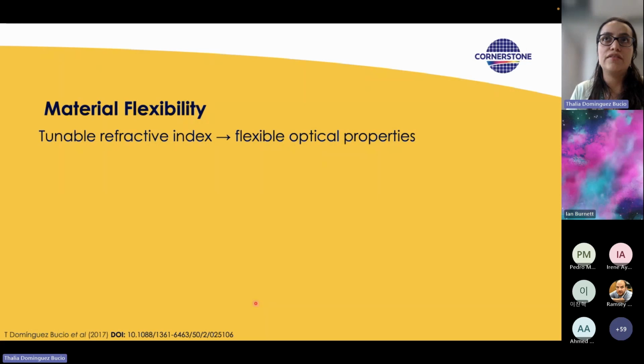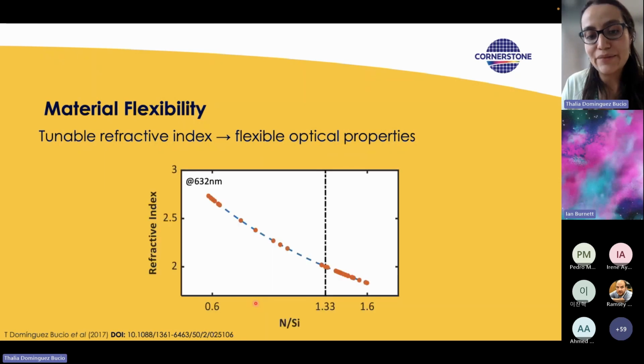the deposition process. So during the moment in which you're depositing your layers, either by LPCVD or PECVD, you can tune the gases to get a different composition of silicon nitride that will determine the refractive index, and this refractive index will determine the properties of your layer. So in this case, typically you can tune the refractive index of silicon nitride all the way from, let's say, 1.7 to 3.